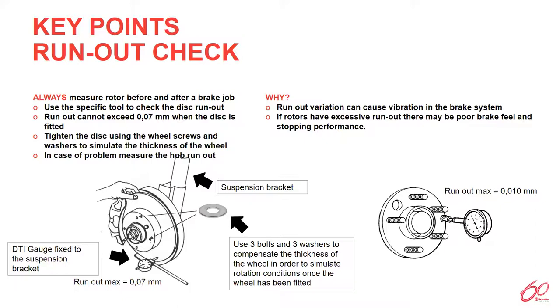If it's out of tolerance, it's recommended to clean the surface of the hub to ensure that it is free of corrosion and to take that measurement again with that new brake disc. If it is still out of tolerance, there could be a mechanical issue with the hub. Therefore, a measurement of the hub is recommended. The maximum runout tolerance of the hub is no more than 0.01 millimeters. If the measurement exceeds this, it is recommended that the hub is replaced. Otherwise, this would lay the foundations for excessive lateral runout that will cause excessive DTV in 2,000 to 5,000 driven miles.